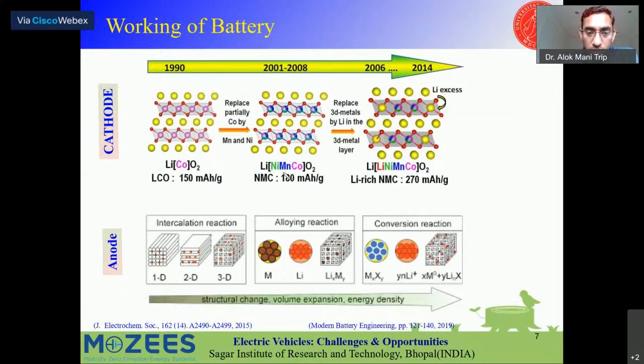Even at present, Tesla is using the same composition, which has the best batteries, and I have shown it in my previous talk. They are using this composition in 811 form. Then another thing is to make this lattice super rich with lithium. If you put in more lithium, which can move in the system, then it could have a higher capacity. So the capacity can go up to 270 milliamp hours per gram with the existing cathode.